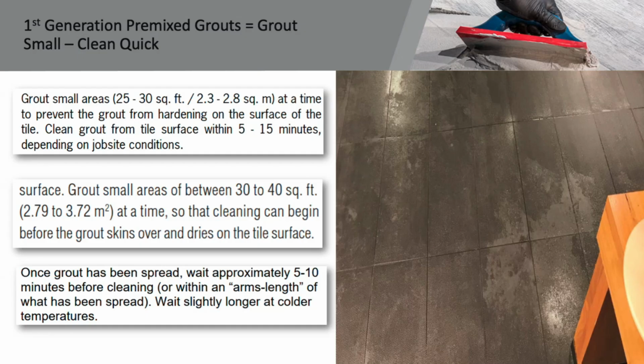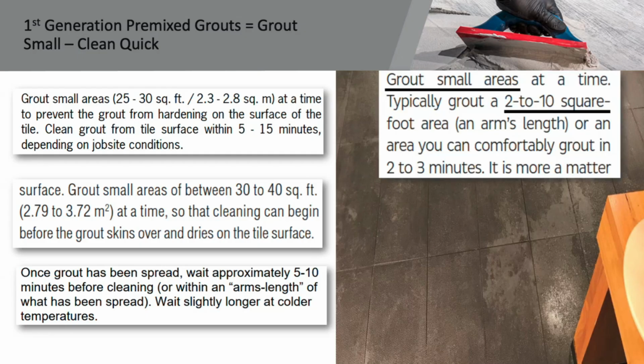The problem is that once that first generation came out, we found that you could not extend that grout area to a larger area like that. So it really narrowed down to about a 2 to 10 square foot area, about an arm's length, or something you could comfortably grout within 2 to 3 minutes.